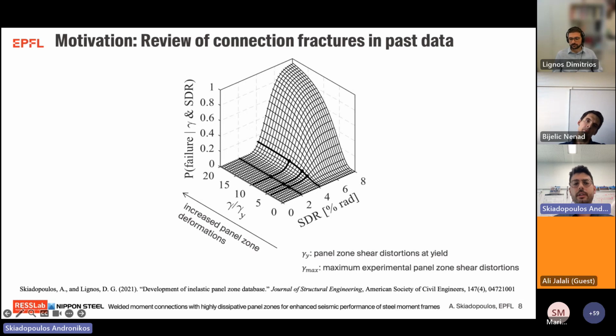However, if we look at the story drift ratio of 4%, which is characteristic of the maximum considered earthquake event, then we see that by increasing the target panel zone distortion from 4 gamma y, which is currently the allowable limit in the design norms, to, for instance, 10 gamma y, then the probability of connection fracture practically does not change. So what this shows, and the research question that arises now, is by how much could we potentially push the inelastic panel zone distortions in terms of seismic design.